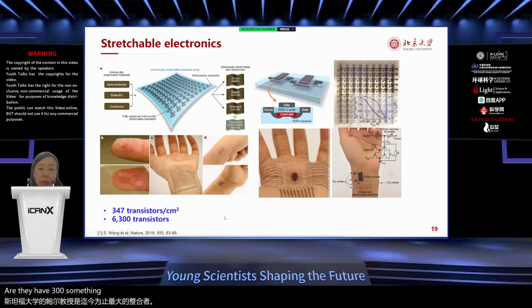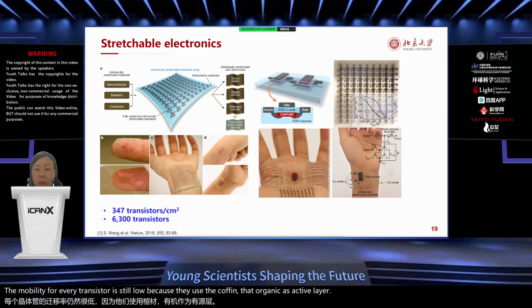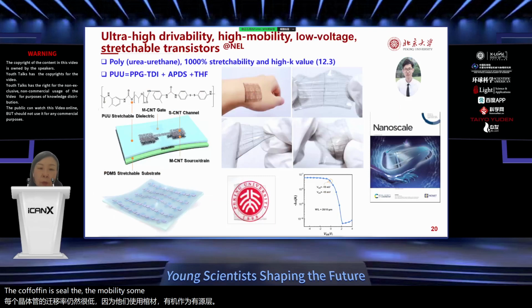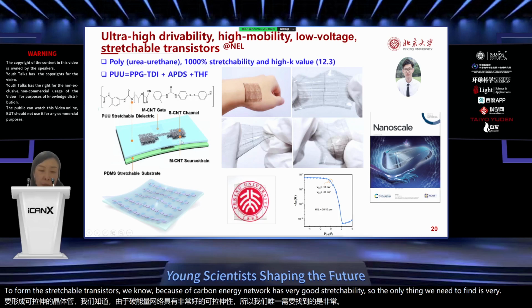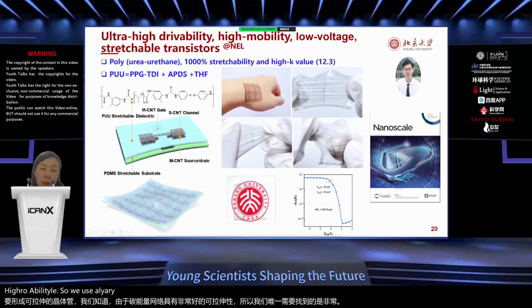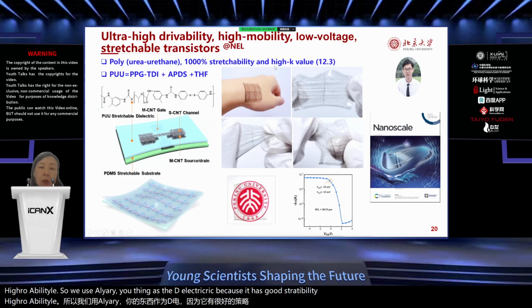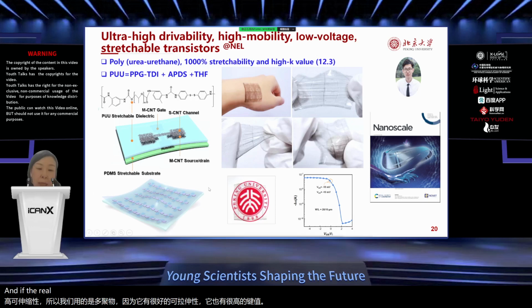They have 300 something transistors per square centimeter, and the total number of transistors for this small system is 6,300. It has very good integration, but the mobility of every transistor is still low because they use an organic material as the active layer, and the mobility is still somewhat low. So we still use this all-carbon frame to form the stretchable transistors. We know the carbon nanotube network has very good stretchability, so the only thing we need to find is a very highly stretchable dielectric. So we use polyurethane as the dielectric because it has good stretchability and also a high K value. And the realized stretchable electronics, you can just stretch it, twist it, and hook it, no problem.